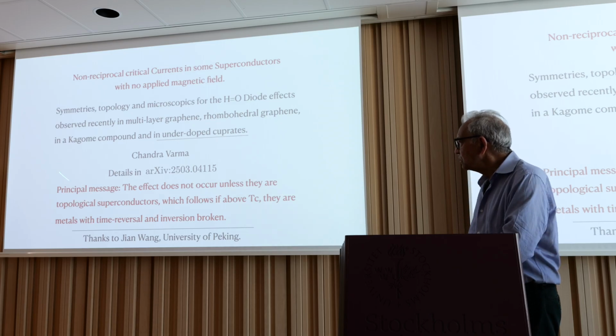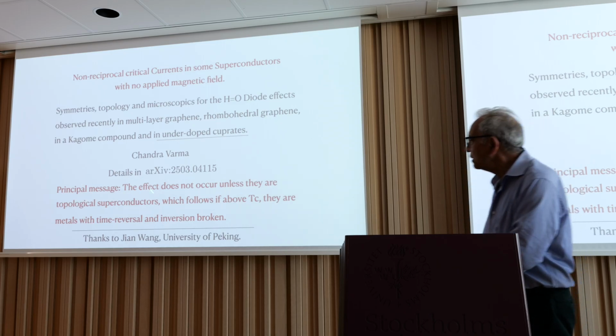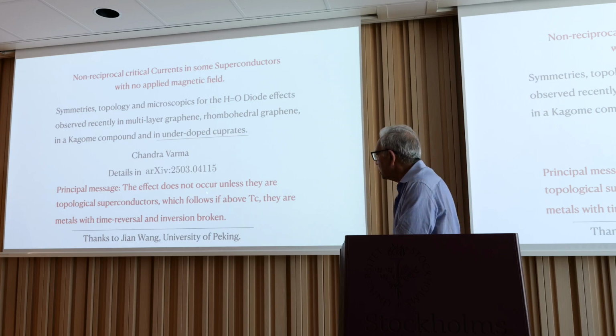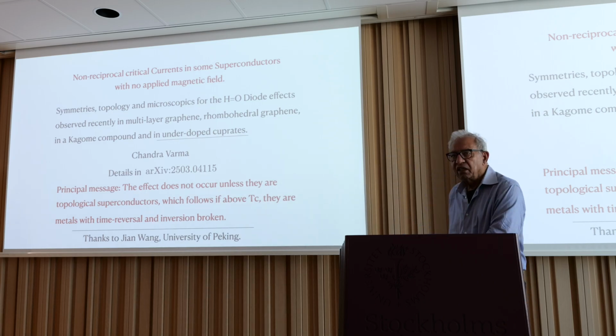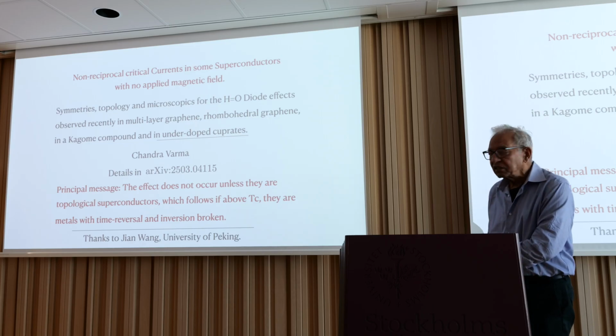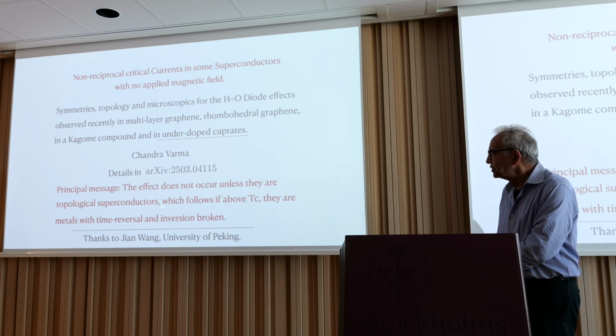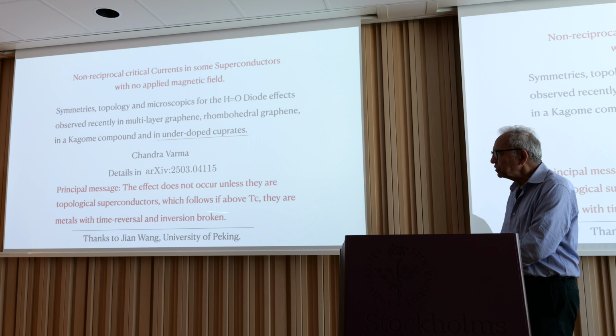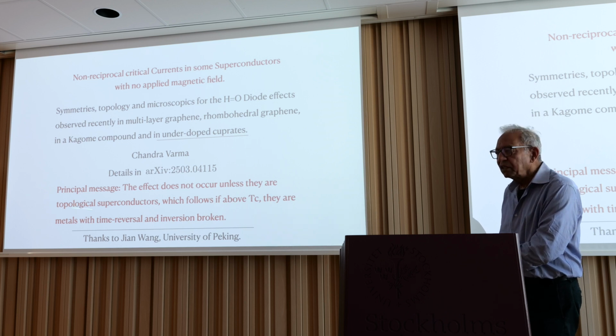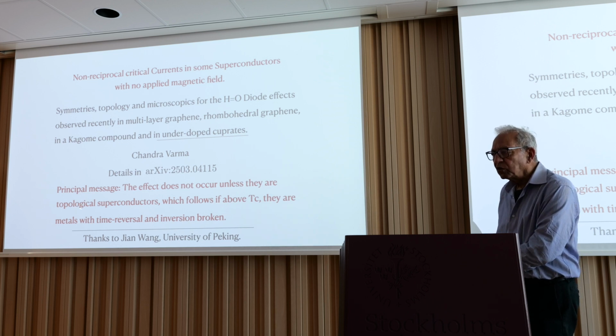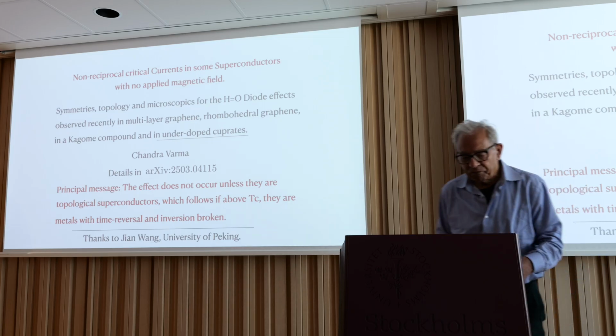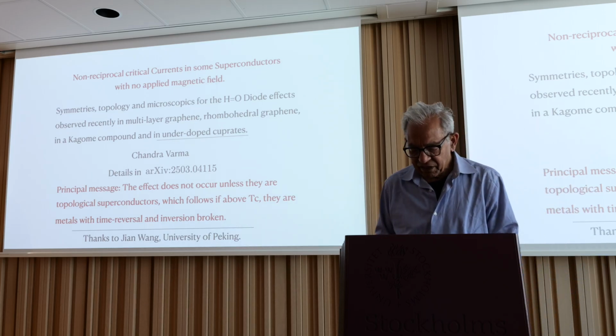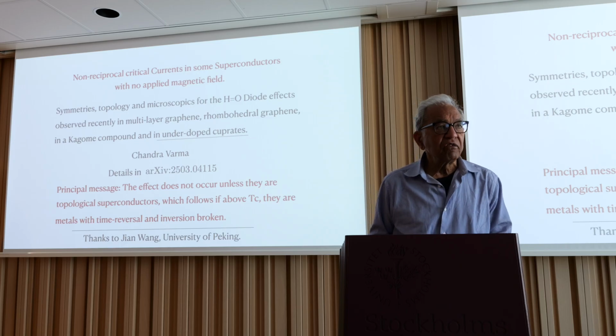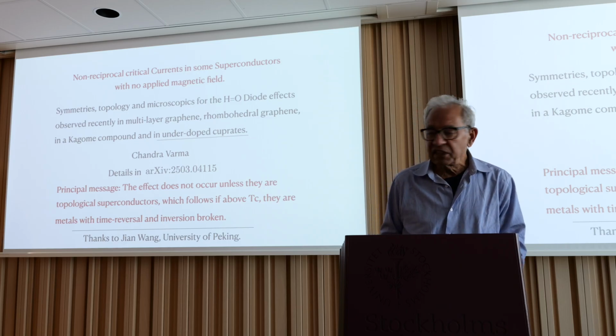The principal message of this talk is going to be that this effect does not occur unless they are topological superconductors, which follows if above TC they are metals with time reversal and inversion broken, which in effect means that these materials should have properties with the symmetry of the anomalous Hall effect already in the normal state.